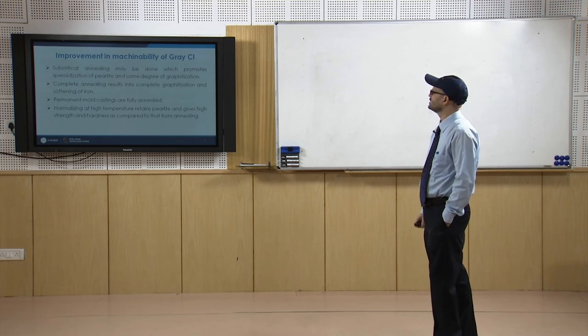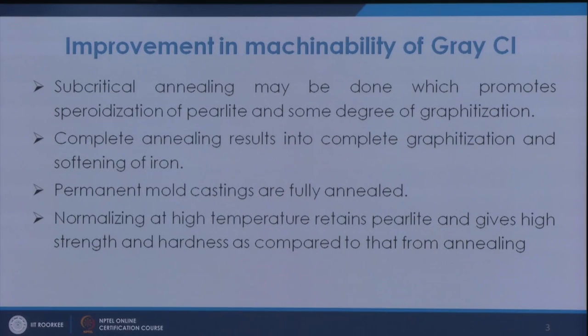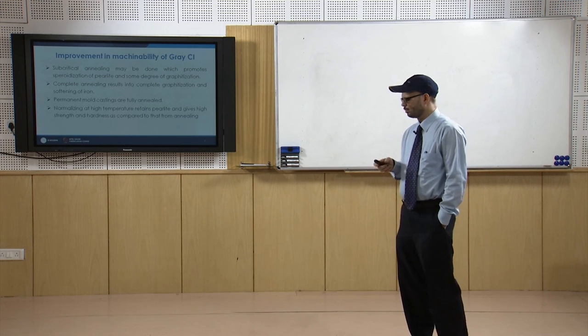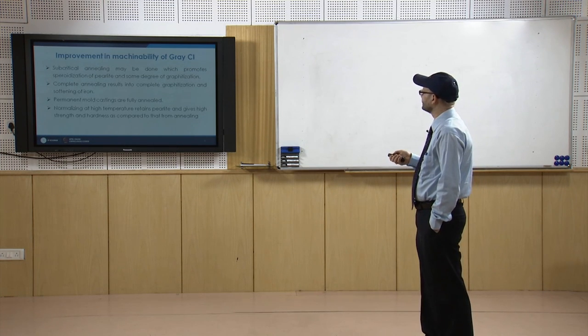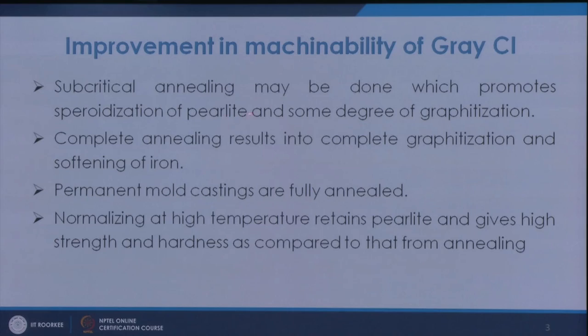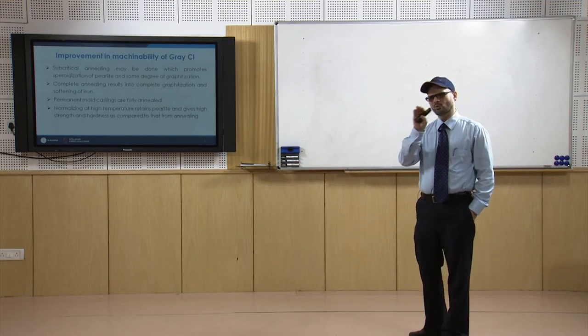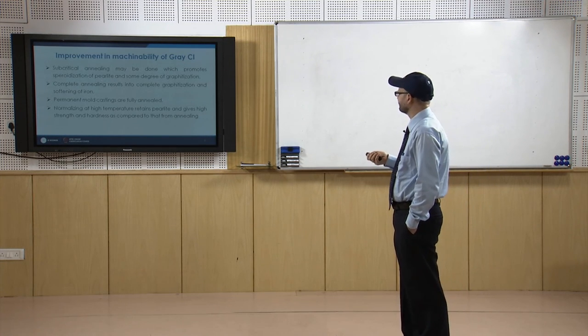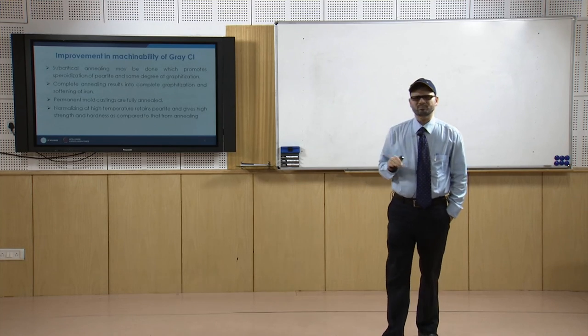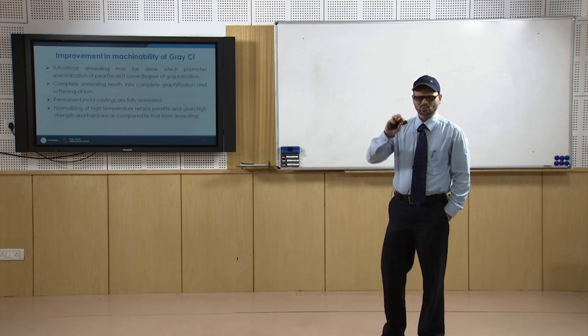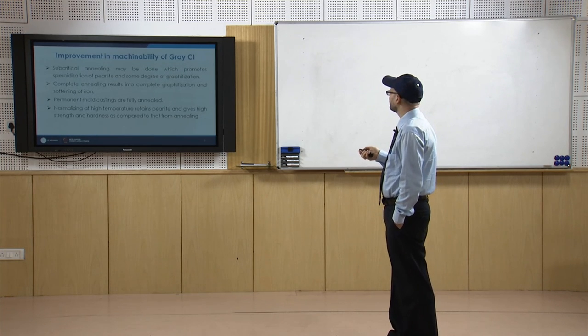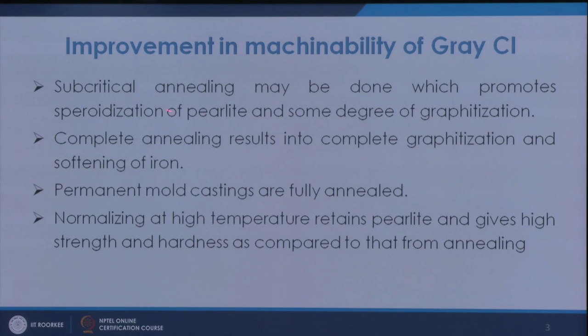Now, improvement in the machinability of grey cast iron. We know that for improving the machinability, normally we go for the annealing process. In that case, subcritical annealing may be done, which promotes spheroidization of perlite and some degree of graphitization. Here, below the lower critical temperature, maybe about 600 to 700 degrees C, we heat and hold at that temperature; that is subcritical annealing. Holding for a larger amount of time leads to the formation of spheroids of this perlite. That is known as spheroidization of perlite.